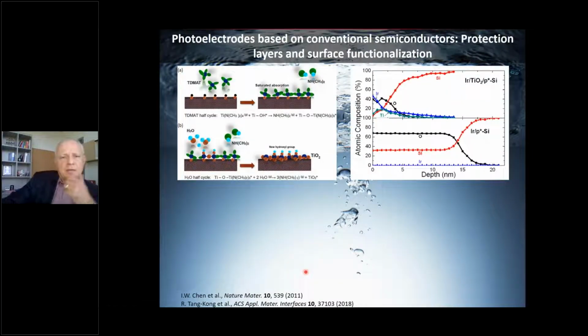So in terms of stabilizing the surface through other means, coatings is an obvious approach, and one particular approach that's gained considerable interest and has been shown to be quite widely applicable is using a technique called atomic layer deposition to coat the surface of otherwise unstable semiconductor materials and therefore to prevent them from exhibiting this kind of corrosion under water splitting conditions. So this is a schematic of the ALD process for deposition of TiO2 using a standard precursor, tetrakis(dimethylamido)titanium, and water vapor as the co-reactant.